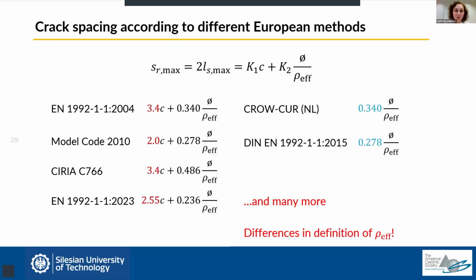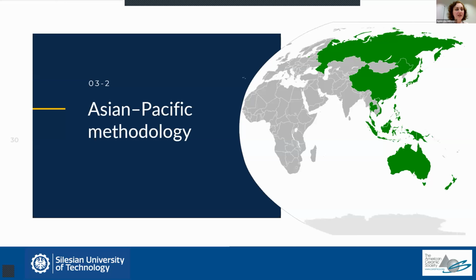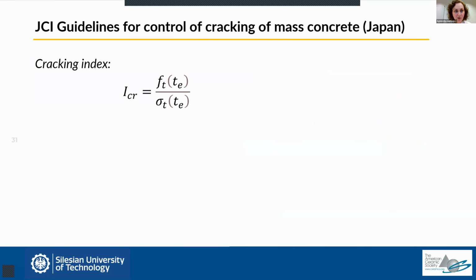However, there are other approaches used worldwide, which can be classified into groups depending on the location. The second group I called Asian Pacific methodology, because these concepts are developed mostly in Australia and in Japan, and they are applied in various countries of the Asian Pacific region. The first approach was proposed by the Japanese organization, Japan Concrete Institute, and this approach is based on FEM-based calculations and statistical analysis. So in this approach, it is first required to determine the so-called cracking index.